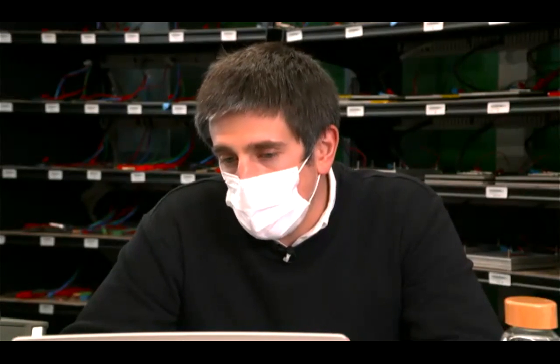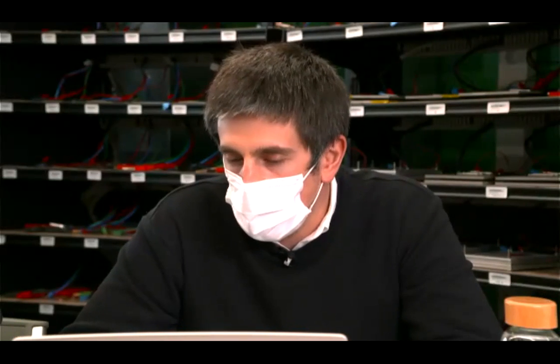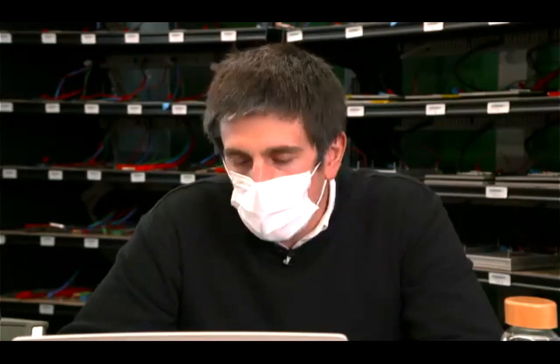So for the current density, the standard formation cycle is usually at lower rates, for example at C/20. So this formation of the cell takes around 2 days with this rate. But of course, it depends on the formation cycle that you want, because sometimes you want a longer cycle or more than one cycle. This is up to the conditions that you agreed in the project, or you want to select, because you want to be sure that the forming is completed. So it depends on that, but the standard one is C/20.